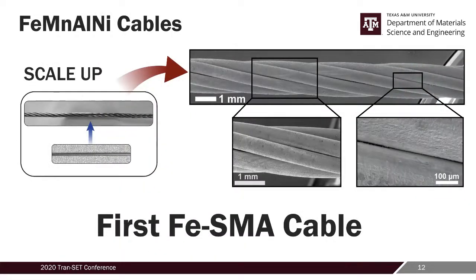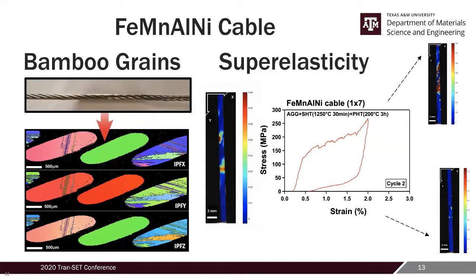Then after we developed the small diameter wires, we developed the first iron-based SMA cable that shows superelasticity in the literature, using iron manganese aluminum nickel cables. On the right, you can see an SEM image of this cable. We used 7 different wires and braided them together, and we fabricated this using the setup that I showed you earlier. And again, the microstructure is very important. We apply heat treatments to these materials, and this graph shows the microstructure of a cable. You can see our grain size is higher than the smallest dimension of the component. And when you test the material, we were able to obtain superelastic response.